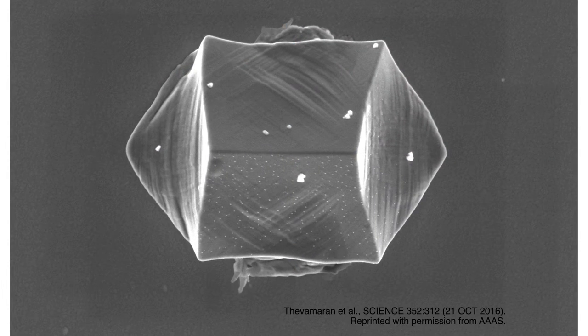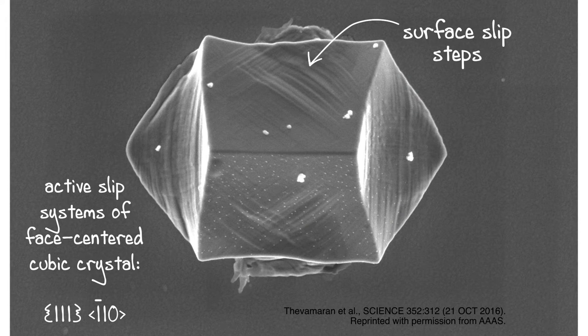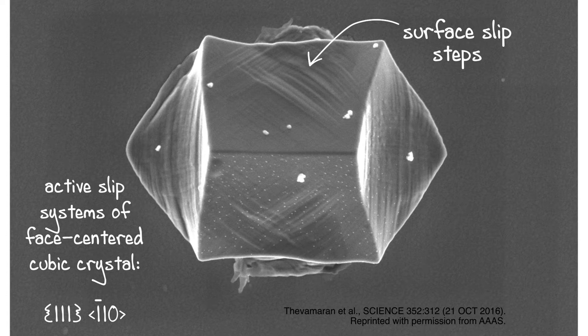If we take a closer look at the surfaces, we notice surface slip steps that have formed due to the active slip systems of the intrinsic crystal structure.